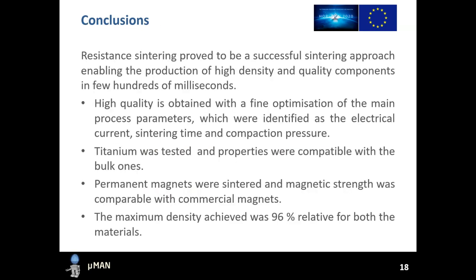So, resistance sintering proved to be a successful sintering approach, enabling the production of high density and quality components in few hundreds of milliseconds. High quality is obtained with a fine optimization of the main process parameters, which were identified as the electrical current, the sintering time, and compaction pressure.